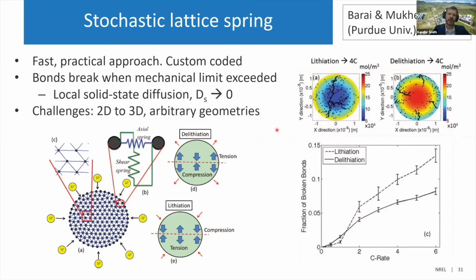But it's a very practical model, and so you can describe the behavior of single particles at different lithiation conditions. Under lithiation, it predicts that you would have tensile stress close to the center of the particle, and that can drive fracture at the center of the particle, which propagates to the edges, or the opposite during delithiation. In this case, you get tensile stresses close to the outside of the particle, which then propagates inwards. And so the fraction of broken bonds, or with different C-rate simulations, you can determine capacity loss and how that evolves with time. So it's a very practical model. You can develop reduced order models which fit into lifetime models and such from this.